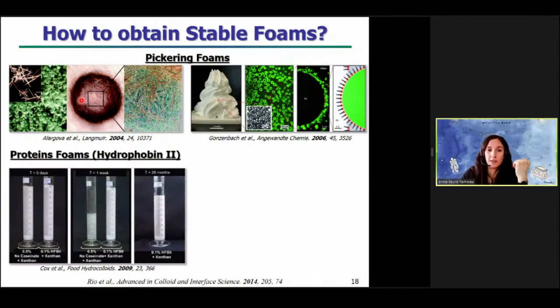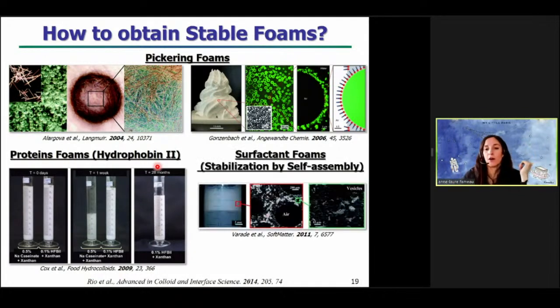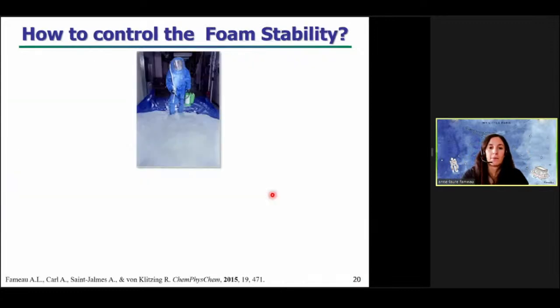You can also use specific proteins when you want to design stable foams. For example, you can use hydrophobin 2. It's a specific protein because it forms a very elastic layer at the interface, stabilizing the bubbles against coarsening and coalescence for months. You can also use some surfactants, and more particularly self-assembly of surfactants, such as vesicles you can see here, because these vesicles are completely crowded between the bubbles inside the foam liquid channels, which slows down the drainage, the coarsening, and the coalescence. So then you can have very stable foam also with surfactant self-assembly. But the main problem with this very stable foam is that for specific applications, you need to control the foam stability. So here you have a picture of a guy that is using a foam to decontaminate a surface.